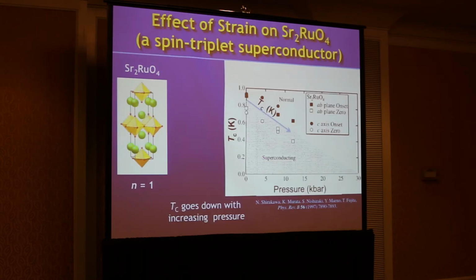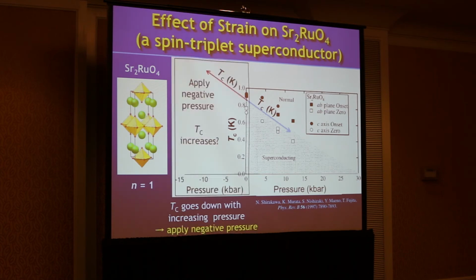The pressure effect on strontium ruthenate was looked at many years ago, and this material is superconducting in the vicinity of 1 Kelvin, and a very interesting material it is, as Laura knows well. In bulk, when you put it under hydrostatic pressure, the transition temperature goes down. Well, that's not the direction that we would like, certainly in terms of room temperature applications of these quantum materials, or making your quantum computer. We'd like to go up. And so you might think of negative pressure. Well, that's something that's difficult. I challenge the next speaker to tell me about how they're going to do that.